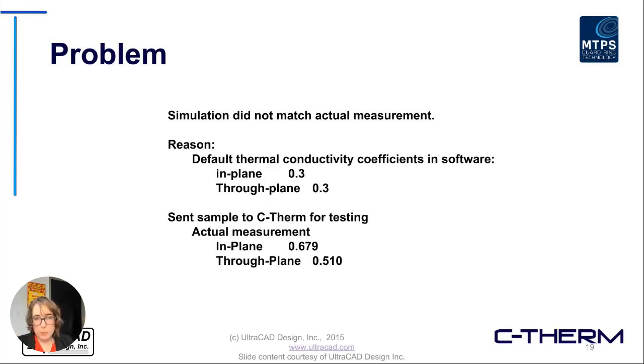And so while he was able to verify that the temperature did appear to be related to the temperature of the trace, he had an issue where the simulation didn't match the actual measurement. It was quite a bit off. So he sent us the sample material for actual testing, and we were able to determine the thermal conductivity of the material both in the in-plane and in the through-plane directions. In-plane was about 0.68 watt per meter Kelvin. Through-plane was about 0.51 watt per meter Kelvin. And we did this with the MTPS test method.